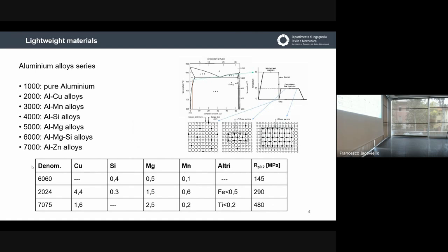So, for example, you can see that in the 6000 series alloy, with this kind of thermal treatment, the resistance increased. The much stronger alloy is the 7075 alloy, for which the values achieved are comparable to steel, common steel. In this way, you can have a material that can substitute steel, but it is much lighter.